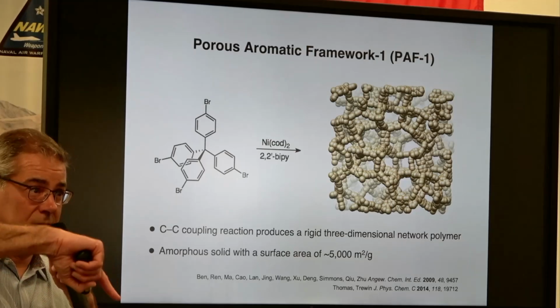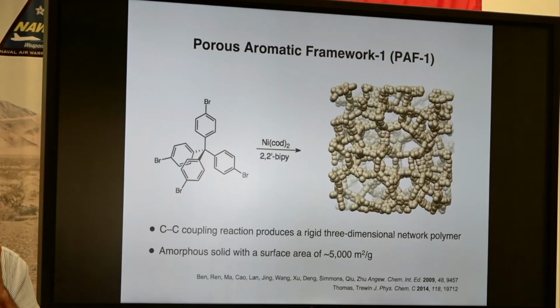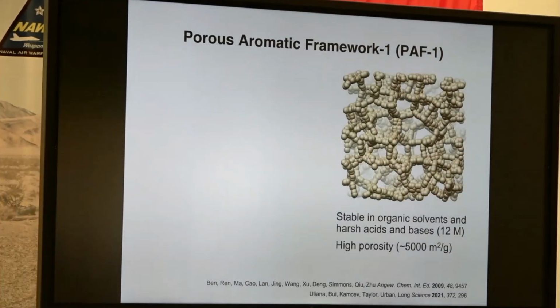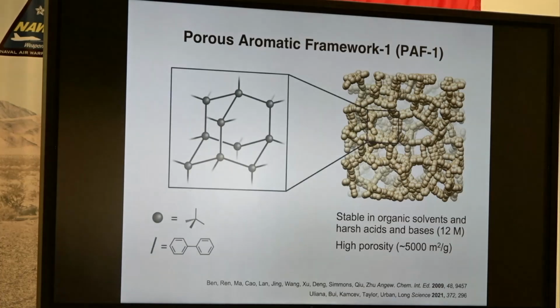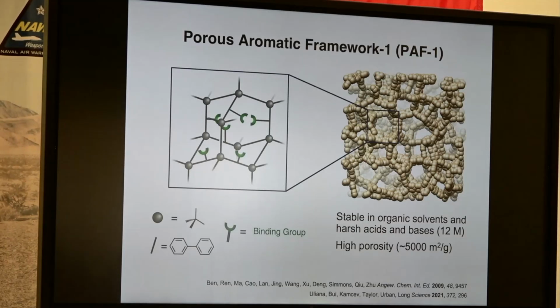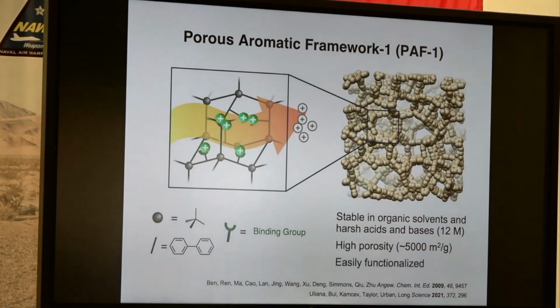This is built up only of strong carbon-carbon bonds in the backbone of the framework. 5,000 meters squared per gram. This is better than most of our MOFs. And importantly, these are robust to very strong acids and very strong bases. So 12 molar conditions, no problem. So the idea is that we can chemically functionalize the biphenyl struts within this network and attach binding groups that could be selective for metal ions. And so we can put in, depending on chemistry, groups that target a specific metal ion that might be present at very low concentrations in a broad mixture of metals in solution.